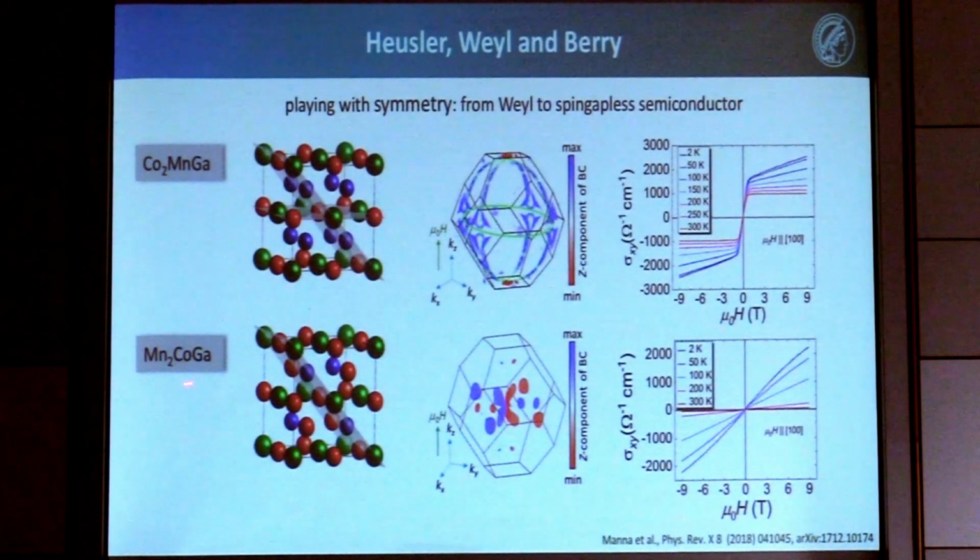You see here we have inversion symmetry and a mirror plane. Here we have no mirror plane. So we immediately allow the Berry curvature to be still large, but having different signs in the Brillouin zone, and this leads to them canceling out. Interestingly, we can make a high magnetic moment in this compound without an anomalous Hall effect. So the anomalous Hall effect disappears.